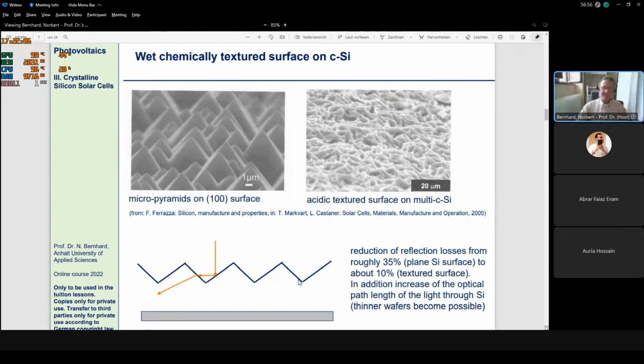The purpose of this structure is always the same, and this is shown in the lower picture. You see it here, it symbolizes the structures as pyramids, but of course it would be the analogous element also for the random structuring or random texturing of the multicrystalline material. You see, if a light beam comes here, if the surface would be smooth, a certain percentage of this light beam would be reflected. And here you see the reflection would go into this direction, and a part of this reflection still can enter the silicon. That means, you see, by this texturing, we increase the probability that a photon, which might be reflected for the smooth surface, still has the possibility to enter the silicon. And the second is also shown. You see the path length through the silicon on average is increased.